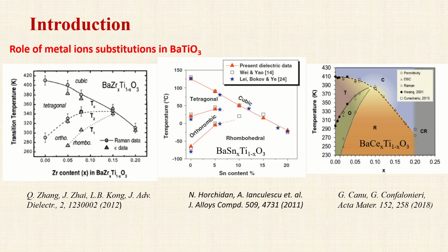The method to modify the temperatures of phase transitions in barium titanate is to substitute some of the titanium ions with other metal ions which are not shifted from the center of the unit cell. Metal ions could be zirconium, tin, cerium, hafnium, but their presence induces similar phase modifications as shown in these phase diagrams.